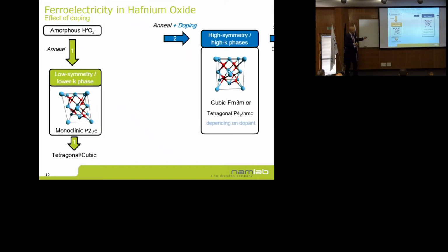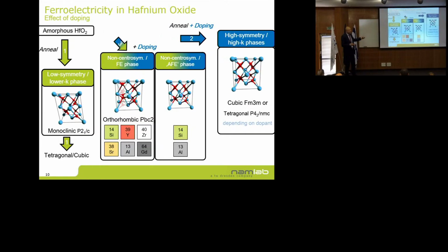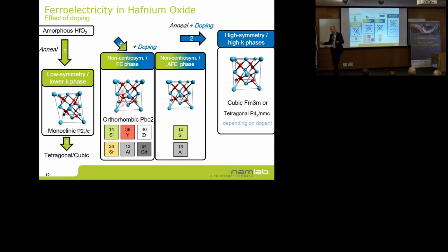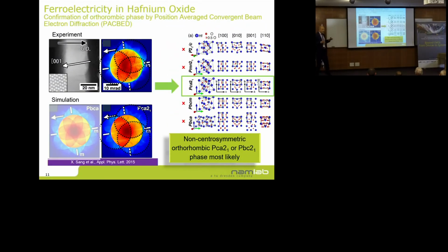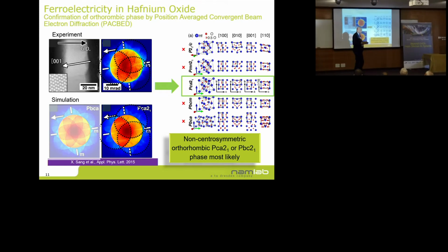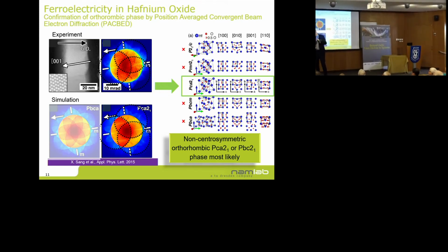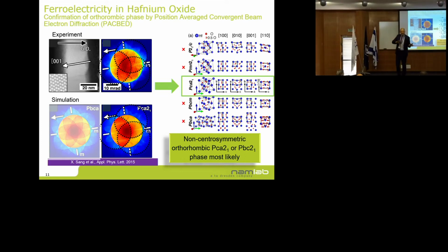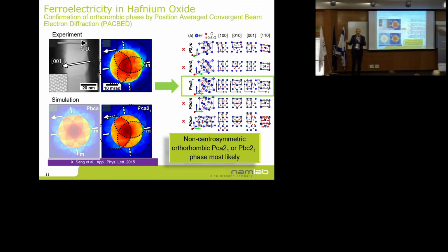And it turns out that exactly at the boundary between these two phases, you seem to be able to stabilize the ferroelectric orthorhombic phase. Yeah, and you can do that with all kinds of different dopants. And for many years, it was a little bit speculative because with XRD data, you cannot really discriminate between phase mixtures of all three phases and only mixtures of monoclinic and tetragonal phases.